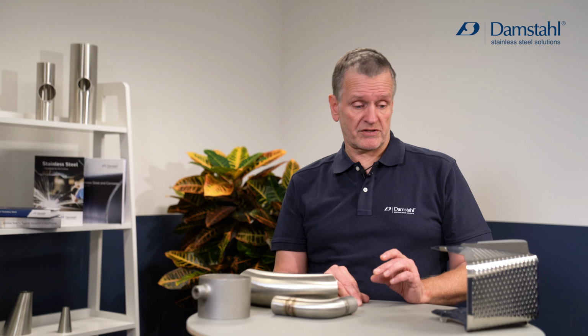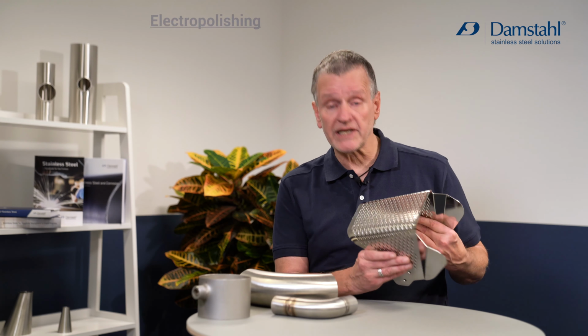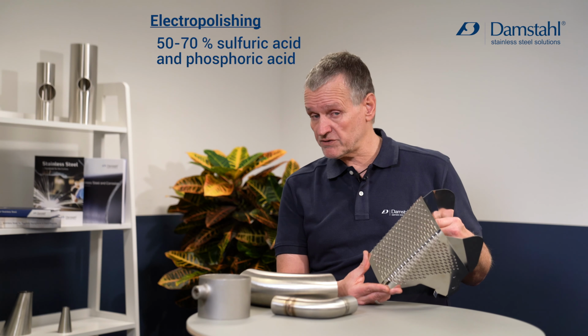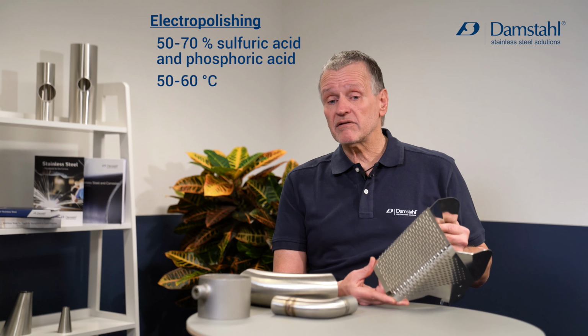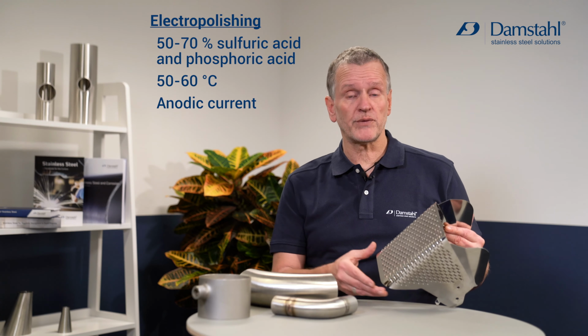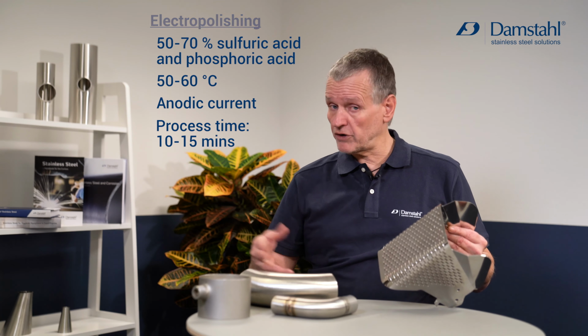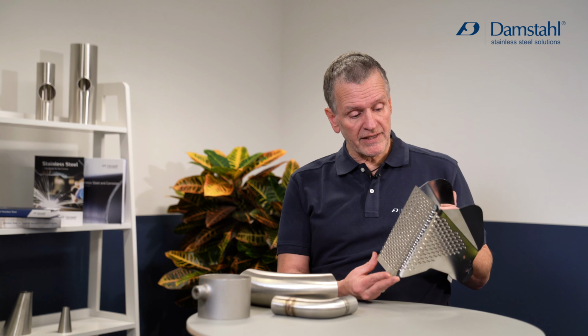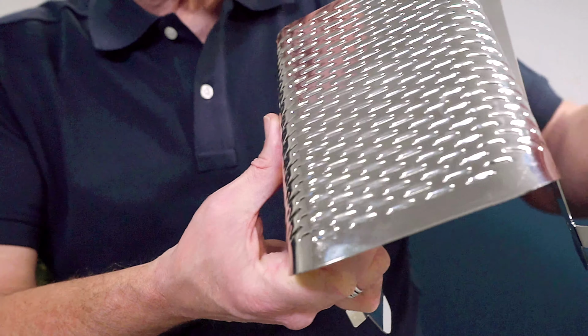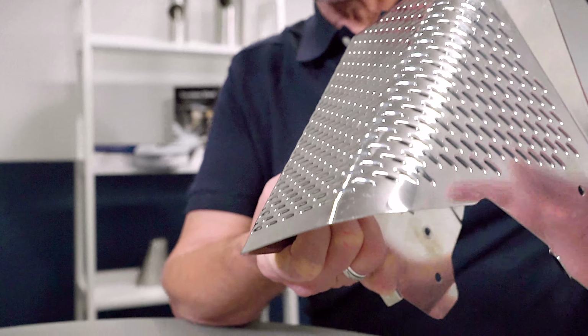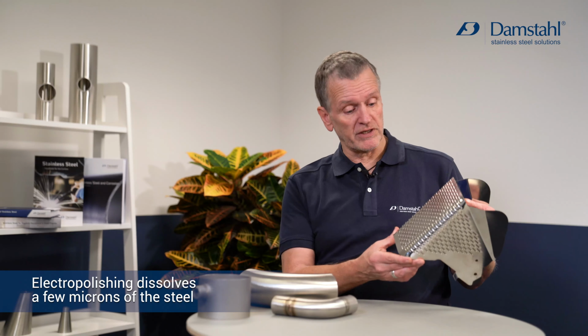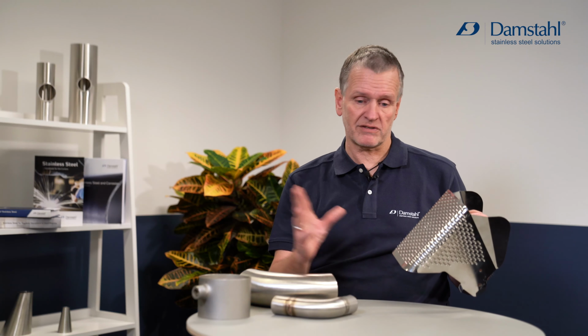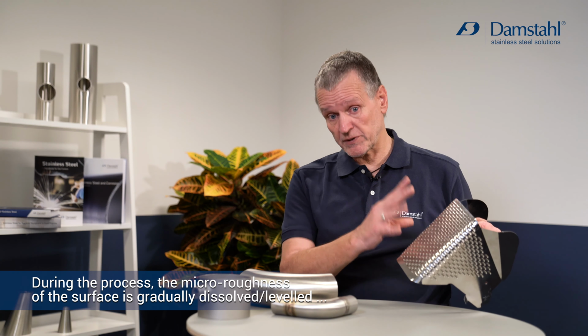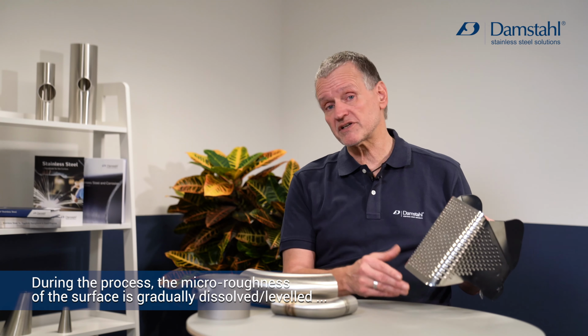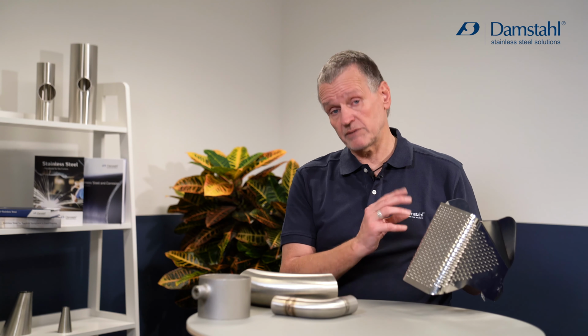And then the most advanced process for chemical surface treatment is called electropolishing. And that's made in a bath containing a lot of sulfuric acid and a lot of phosphoric acid, usually at a pretty high temperature, and then an external rectifier to push a lot of current through the system. And in the end, after like 10-15 minutes of treatment, you get this super bright surface, which on the one hand looks incredibly nice, and on the other hand has the absolutely best corrosion resistance you can get from this particular type of stainless steel, usually applied to the austenitic stainless steel of the 304 and the 316 class, but even the ferrites and the duplex steels can actually be electropolished as well.